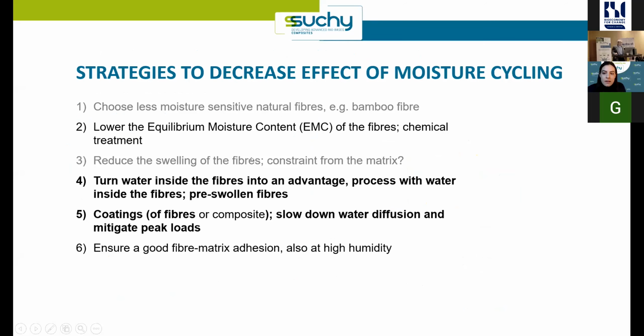So here are some strategies to decrease the effect of moisture cycling. You see there are quite a few strategies, like using fibers that are maybe less sensitive. But in the SUCHY project, we particularly looked at a few things. That is here actually number 4, where we try to see if we don't dry the fibers. So if we have them already pre-swollen, would that give benefits for the durability, because they don't have to swell all the way from a super dry condition? And indeed, that seems to have some benefits, as we will show. Another thing is to work with coatings, either for the composite, but specifically also for the fibers, to put some kind of barrier inside the biocomposite. We have also looked at some other treatments, but I'll mainly focus on these 2 aspects.